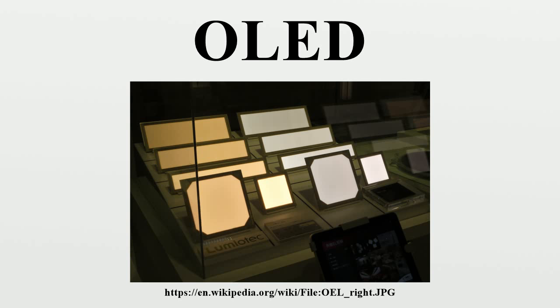For example, electron-only devices can be obtained by replacing ITO with a lower work function metal, which increases the energy barrier of hole injection. Similarly, hole-only devices can be made by using a cathode made solely of aluminium, resulting in an energy barrier too large for efficient electron injection.